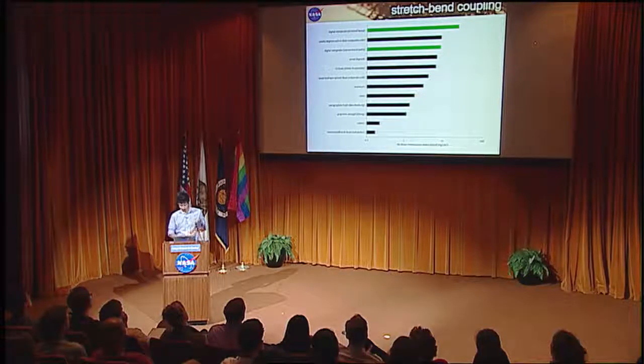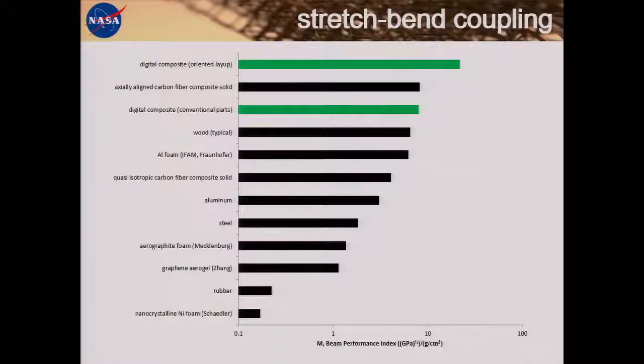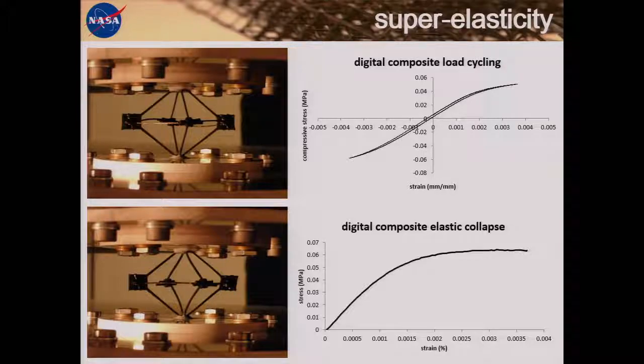So here we see that we've achieved in experiment a better performance than conventional aerostructure materials. So this is based on the linear elastic regime, which is generally considered to be the useful bit. And when you exceed the linear elastic regime, we do see a non-dissipative superelastic mode. And so this, I won't go too much into detail here, but what you see is